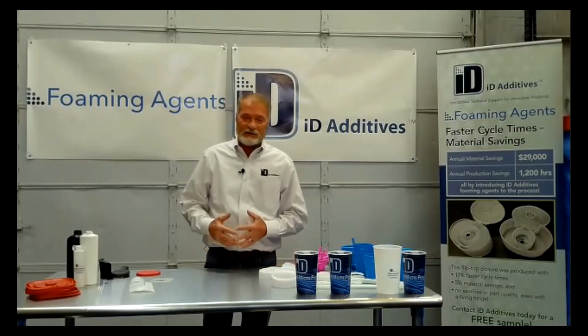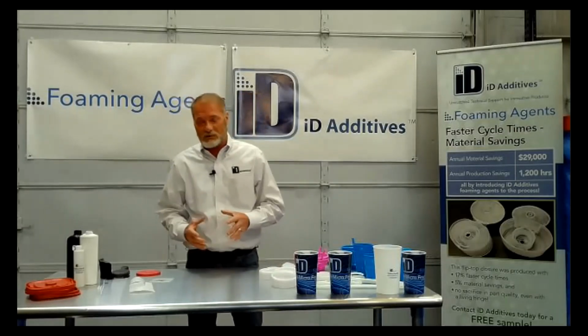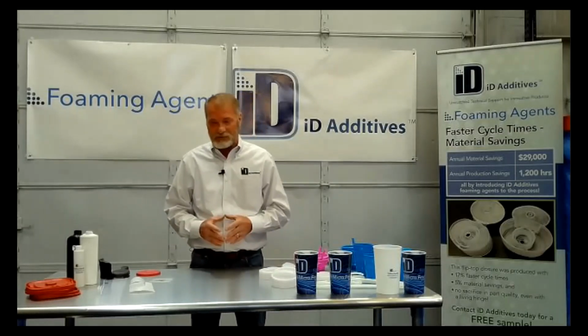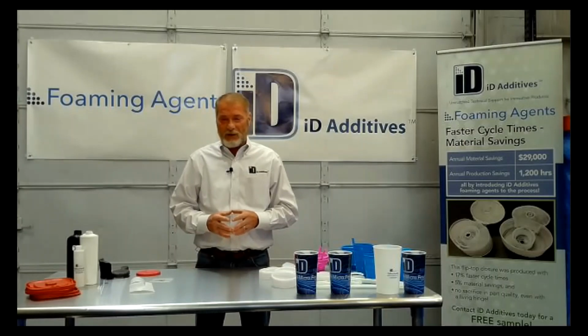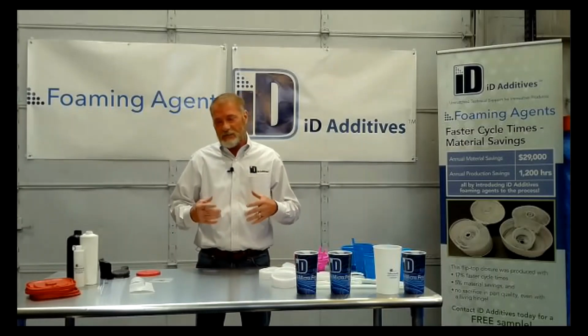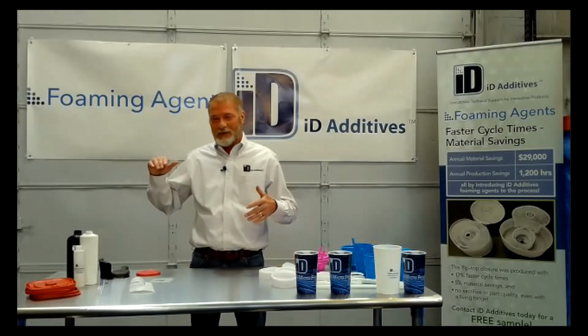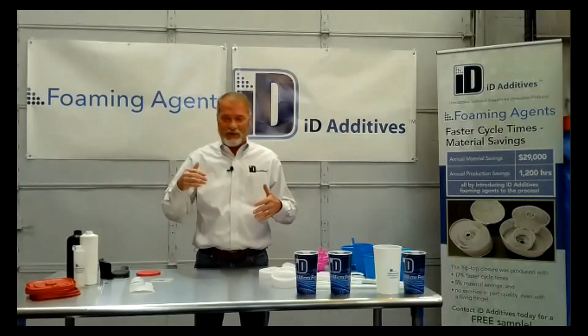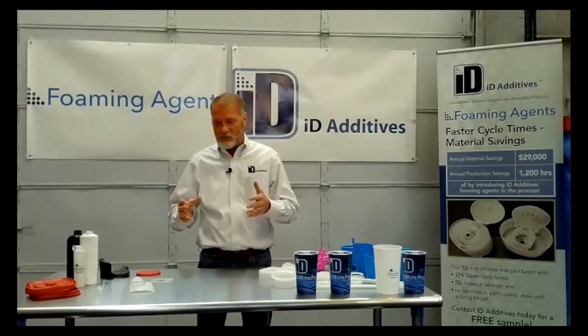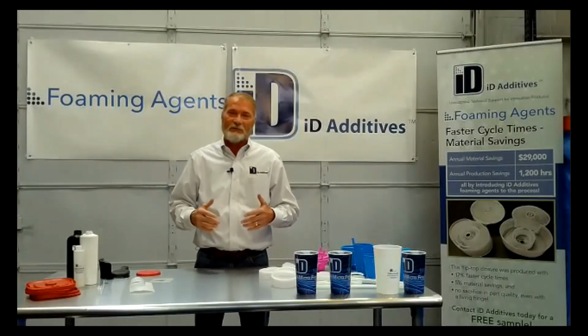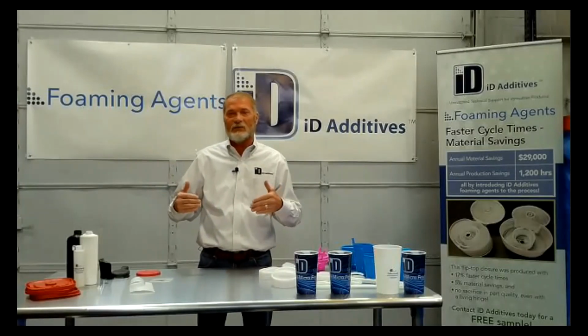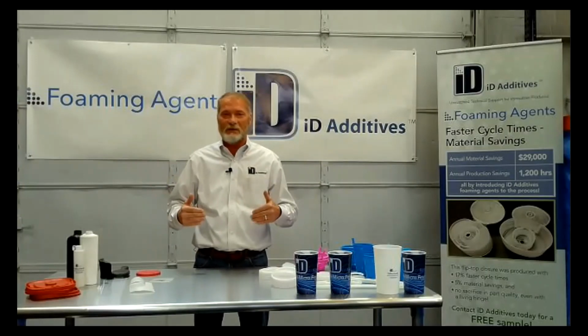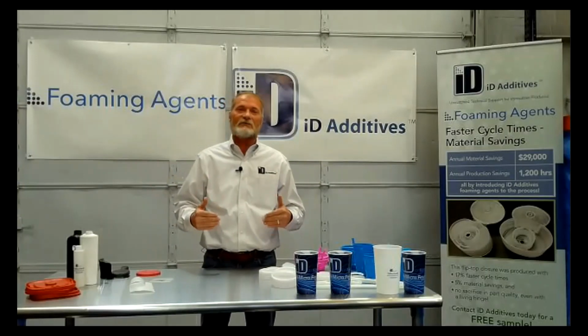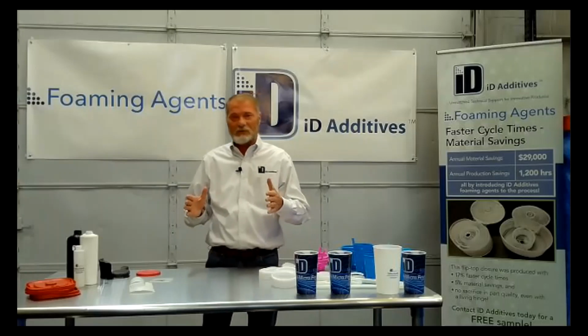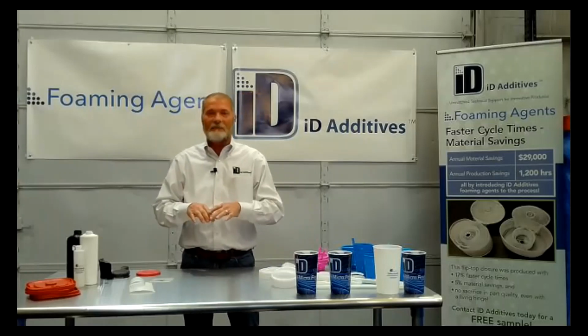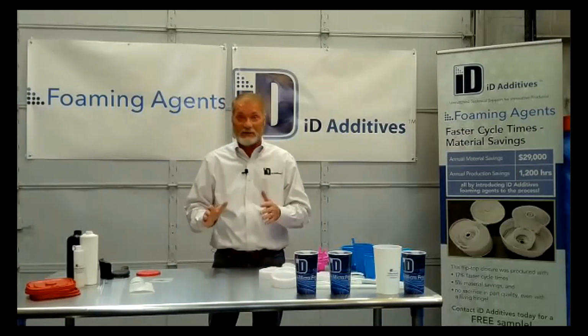I had a customer that was molding this little red part, with an inch and a half screw. The problem was he wasn't getting very much foam. It was about the time it took for that foam, and it just went very quick through it. I thought it was temperatures, but it really wasn't. What it turned out to be was it was going too fast through there. So we had to open up the cushion so that he had more time for the foam to go off in that cushion space.